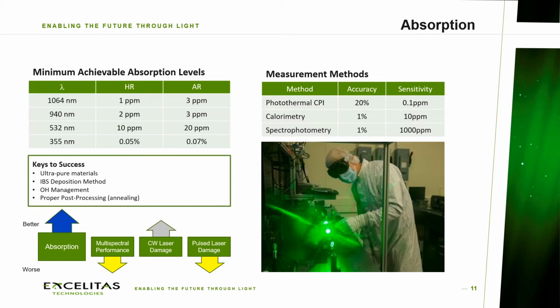Calorimetry in particular can be done with a very high level of accuracy, but its sensitivity starts to get somewhat challenging and/or prohibitive around 10 parts per million. Spectrophotometry is commonly used for absorption, but it's really only appropriate for much higher levels of absorption.